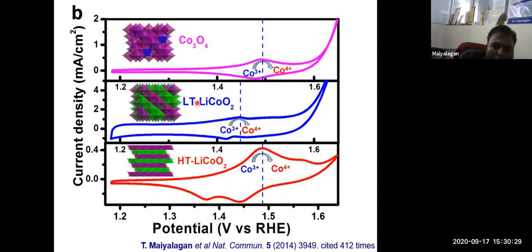So when you look at these three materials, all are the same cobalt materials but with different structures, the redox couple potential also changes. You can see this potential is a higher potential, this is a lower potential. So this redox potential changes. Obviously, you see the oxygen evolution reaction for this low temperature lithium cobalt oxide at a very low onset potential. So this gives a better OER material, you can see here.